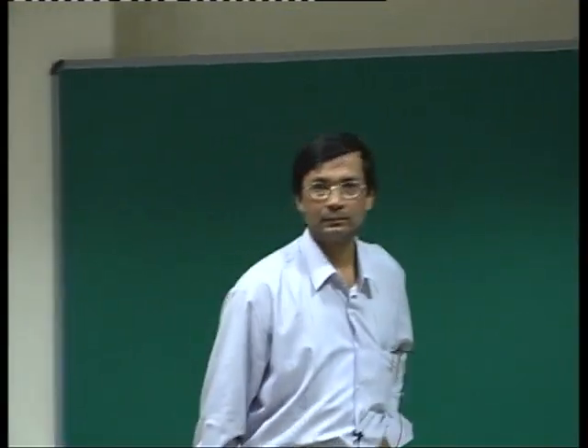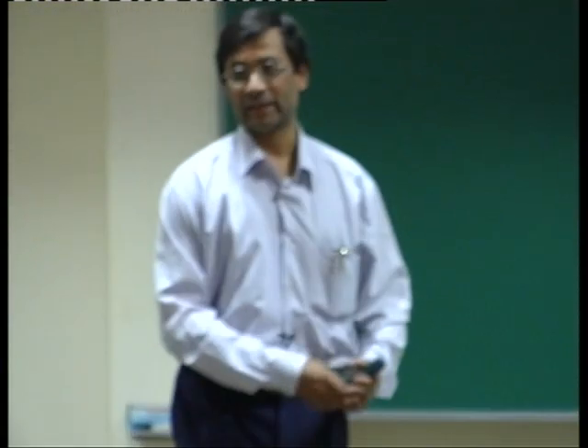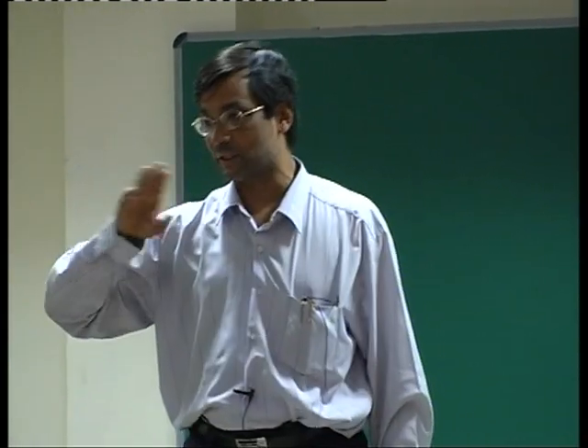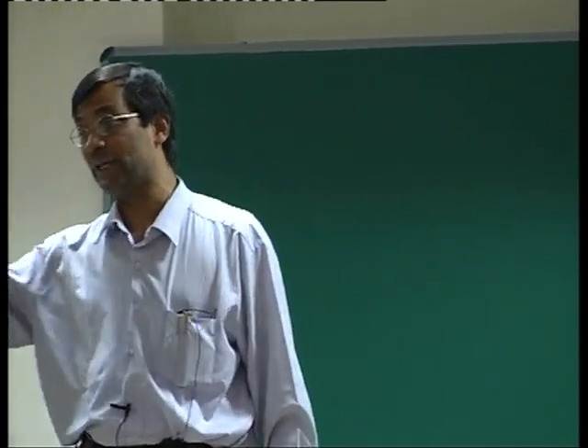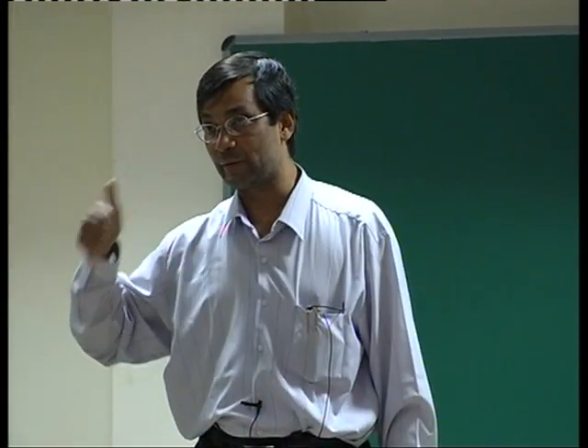Since it's a nearly compensated metal, I was interested if you have done any magnetoresistance measurements. We did some magnetoresistance measurements of this. In fact, for a different reason, when magnetoresistance was very popular in 93-94, we tried with very high fields, also in collaboration with the Japanese. The magnetoresistance is weak. It's not very anisotropic. Single crystal data is available for transport. It's a factor of 3 within each other. If I remember right, along the C-axis is more conducting than along the AB.